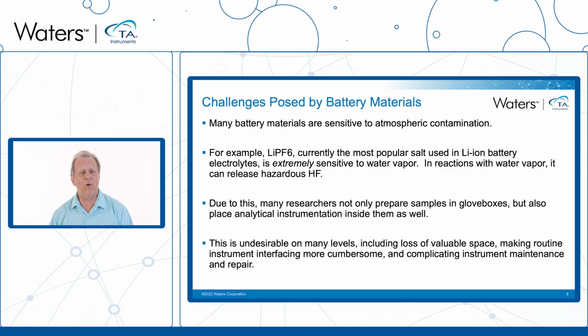Now I'd like to talk for a little bit about some of the challenges posed by these battery materials. It revolves around the fact that many of them are sensitive to atmospheric conditions. That is, reactions with either water vapor and or oxygen. For example, lithium hexafluorophosphate, which is currently the most popular salt used in the electrolyte, is extremely sensitive to water vapor. In reactions, it can release a very dangerous compound, hydrogen fluoride, or HF.